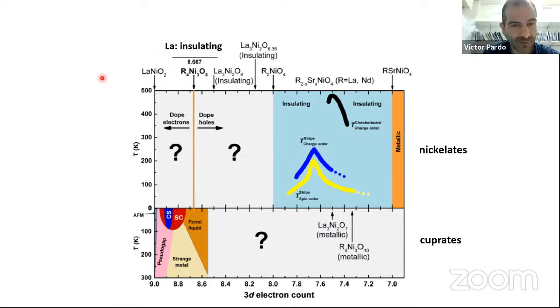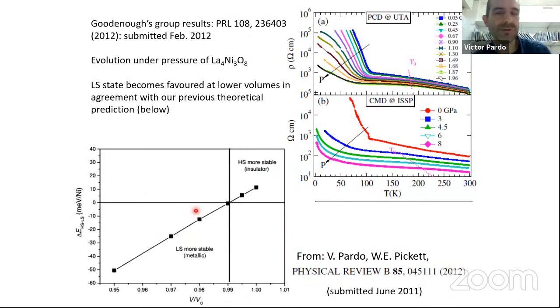So we needed to do something. If we want to get nickelates that are closer to the cuprates, we had to start with a Fermi liquid here at least, or a metal. So we said, okay, what can we do to turn lanthanum 4 3 8 into a metal? Well, what we said, when I was with Warren Pickett in California, was, okay, let's try to pressurize it. We reduce the volume, and we know that by reducing the volume, it is very common in these oxides that the low spin state becomes favored, and with it, metallicity should appear.